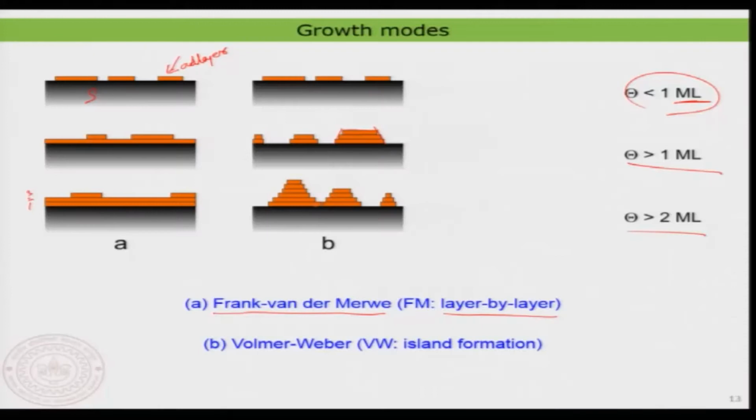If you recollect the example that you have seen for the case of germanium on top of the silicon 100 surface, even when we increased the coverage, whatever you saw was basically islands, but they were growing in height. So, that is some kind of island growth, and of course, if you increase the coverage very high, then you start to see the first layer getting connected, but nonetheless the overall nature of the surface would always look like you have basically islands.